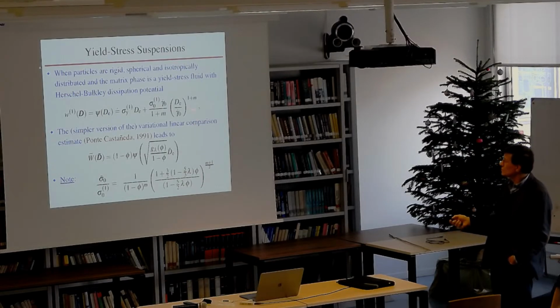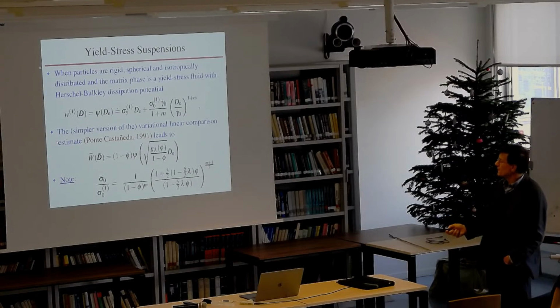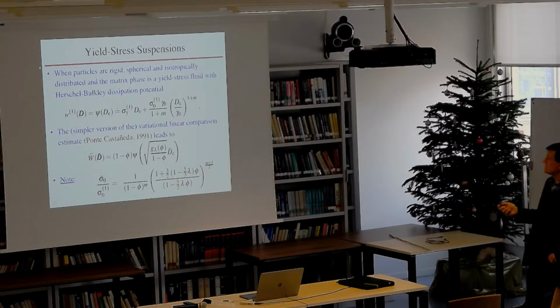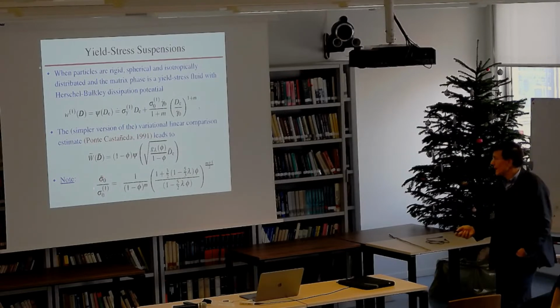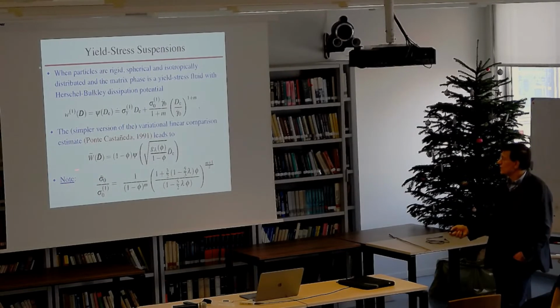This is the Herschel-Bulkley model. This is the yield stress and this is the flow stress. You have both in the same expression, but you can try to generate estimates for both the effective yield stress and the effective flow stress, and that can be described in terms of a power law. If you make use of our old method that gives a bound, you get this simple expression here.